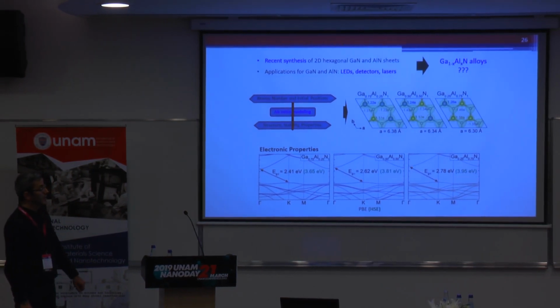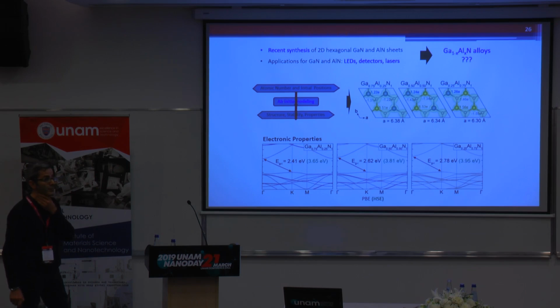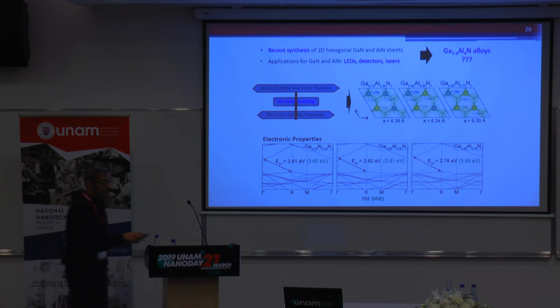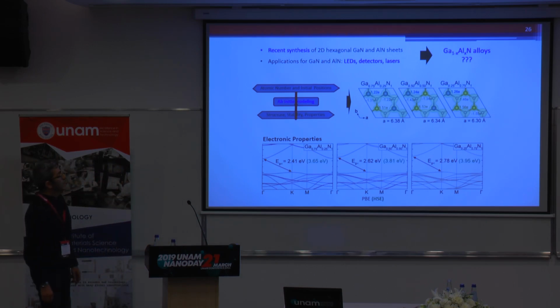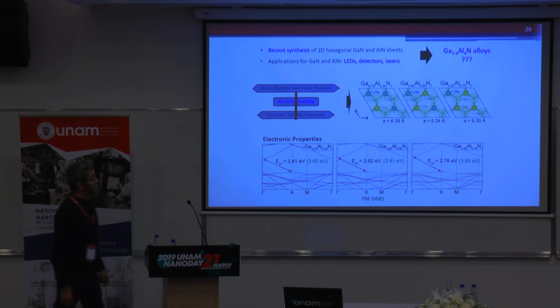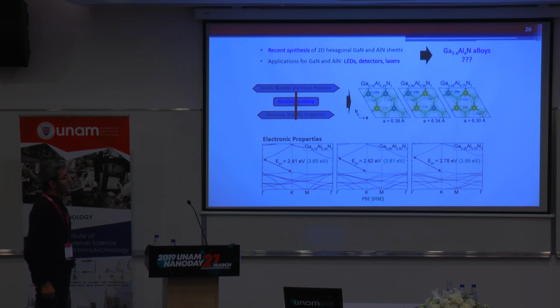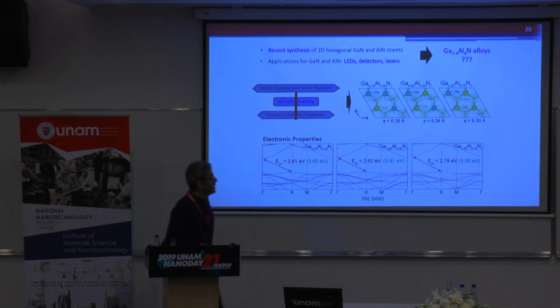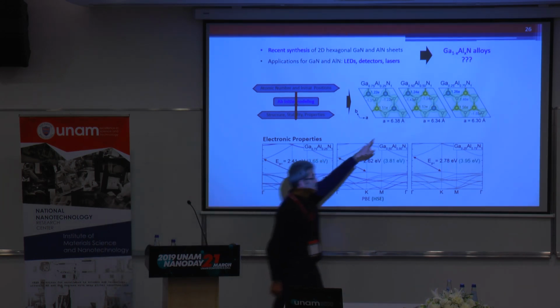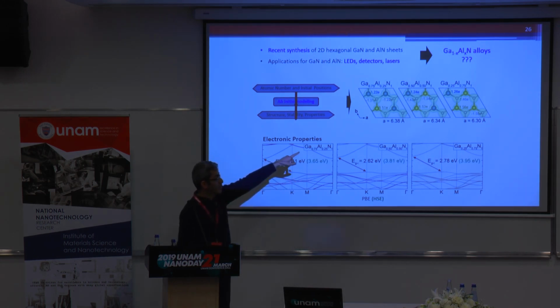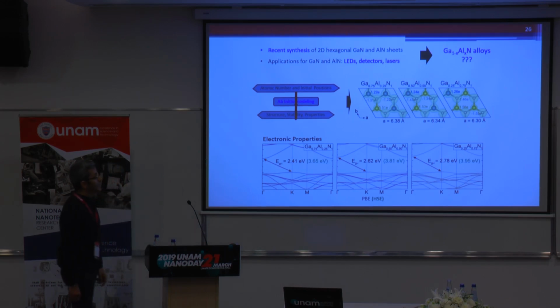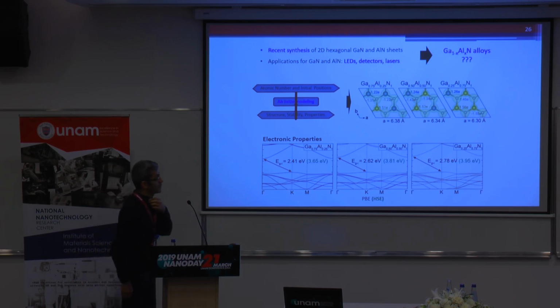Gallium nitride and aluminum nitride monolayers have been studied in many respects, but the monolayer of the ternary alloy has not been studied yet. So our motivation was to see the stability of this ternary alloy and check its characterization. As method, we have used ab initio or first principle methods, namely density functional theory. We used VASP and Phonopy codes and characterized all the properties. Here we obtained the crystal structures of these ternary alloys. The lattice constants show a linear decrease with respect to aluminum content, x. We made phonon dispersion and molecular dynamics calculations to check the stability of these structures.